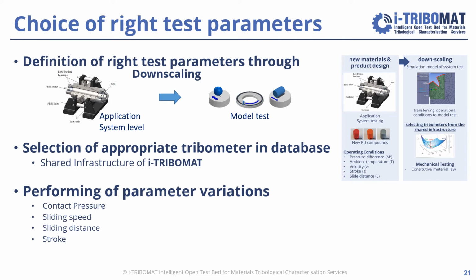So in order to obtain this measured coefficient of friction, you have to first do a downscaling. So you go from the real application, you do a downscaling simulation, and then you can decide which model test configuration and parameters are appropriate. And with that information, you go to the shared infrastructure, to the database where all tribometers are collected, and you look for the appropriate tribometer. Then you perform all parameter variations of interest. You can vary contact pressure, sliding speed, sliding distance, and stroke. And the simulation determines what is needed and tells the experiment people which parameter variations are required. The output values are defined, whatever they change here in terms of parameters.